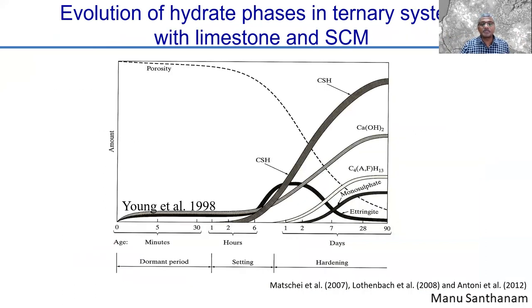So just to show you the chemistry in more detail, what really happens in normal Portland cement is shown here. You have calcium silicate hydrate and calcium hydroxide as the two primary products that are forming in cement hydration. You have in the long term calcium aluminate hydrate and monosulfate, which are the stable phases, whereas ettringite, which is a high volume phase, starts to diminish in the long term and converts to what we call monosulfate.